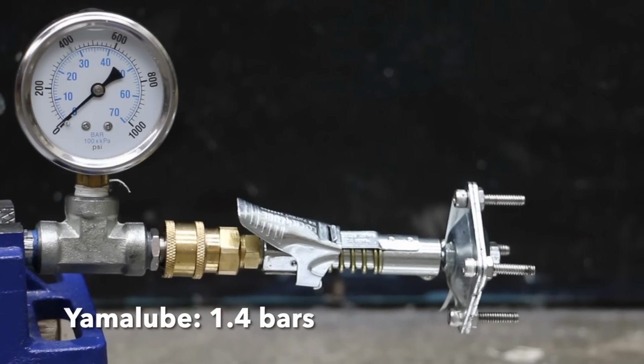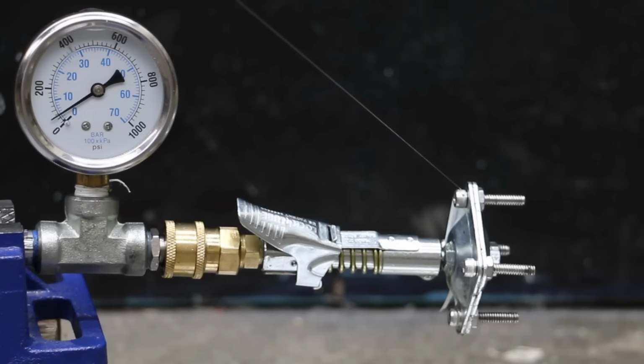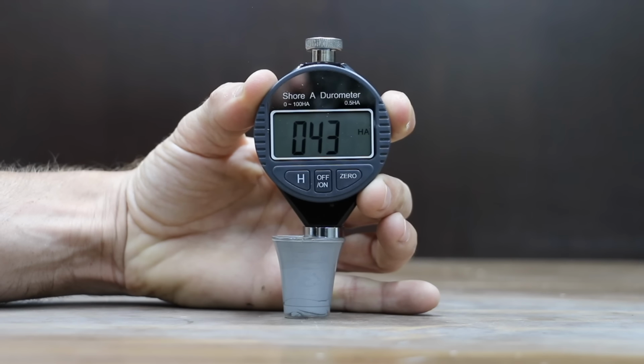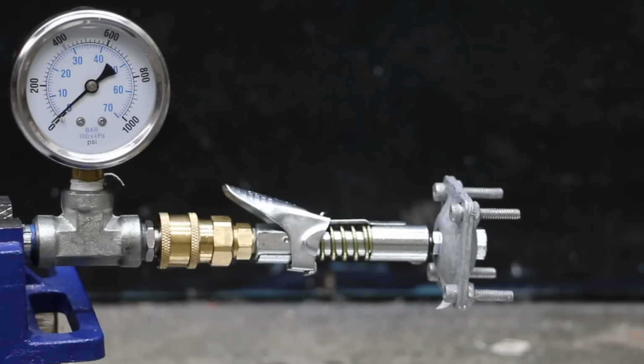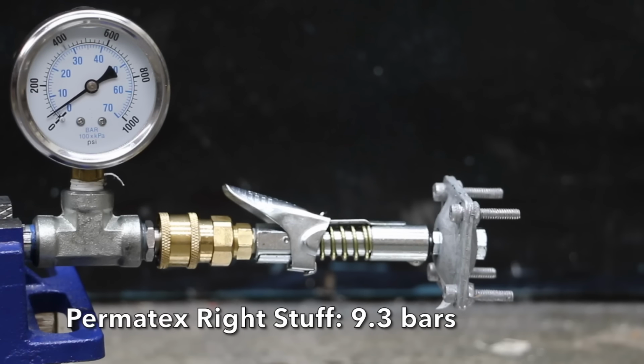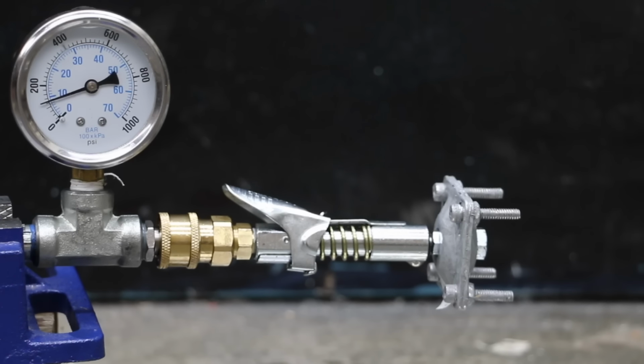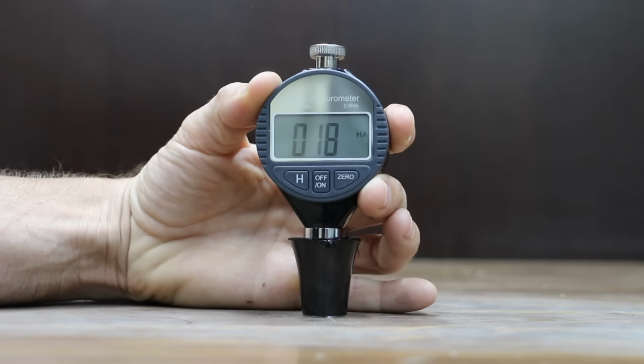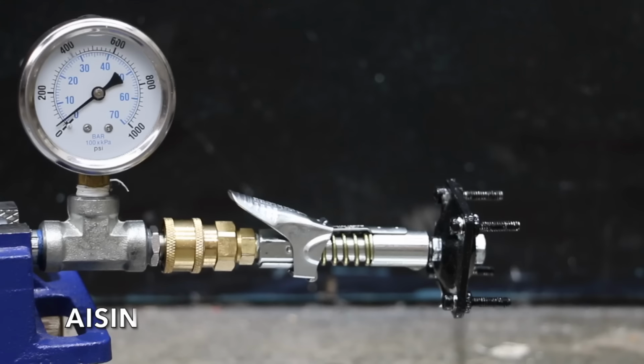And the Yamalube began leaking very quickly at around 20 PSI. And the Permatex Right Stuff is the hardest gasket maker yet at 43. And the Permatex lost its seal pretty quickly at 135 PSI, or 10 PSI better than the Permatex Ultra Grey. And the AISIN is pretty soft at 18 and has a decent tensile strength at 58.4 pounds. And the AISIN began leaking at 520 PSI before topping out at just over 600 PSI.